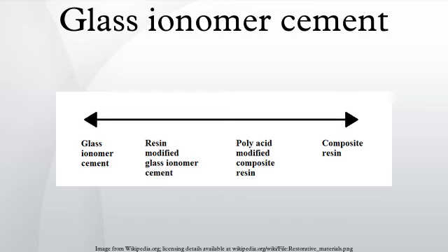Although resin-modified glass ionomer cements show higher bond strength to dental hard tissues than conventional materials, they exhibit variable results in microleakage tests. Not all of them display significantly less leakage against enamel and dentin than their conventional counterparts. This may be partly because their coefficient of thermal expansion is higher than conventional materials, though still much less than composite resins. Controversy also exists as to whether the slight polymerization shrinkage is significant enough to disrupt the margin seal.